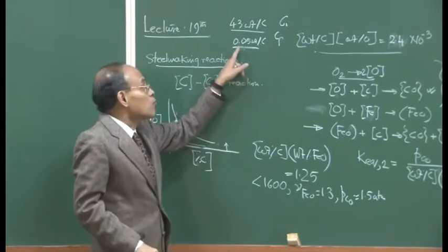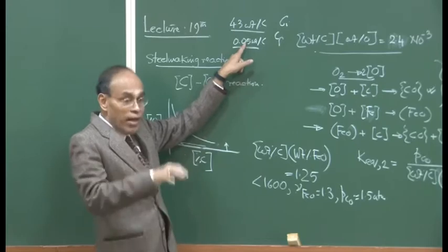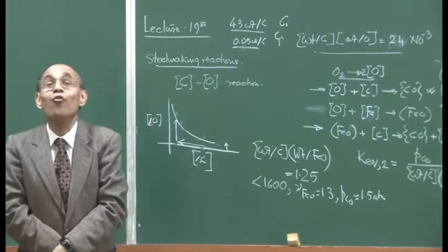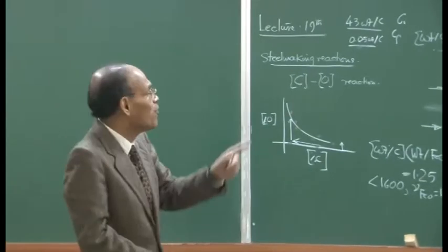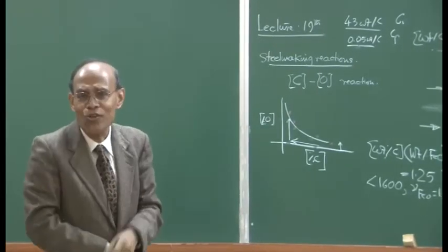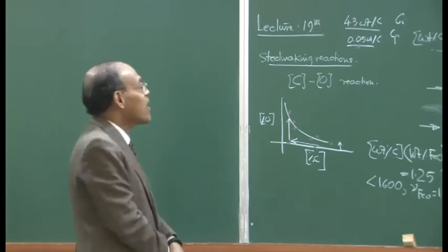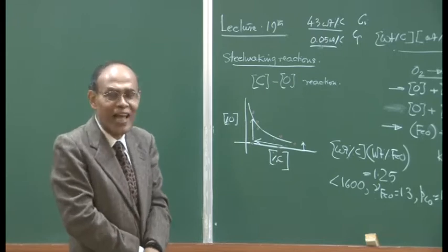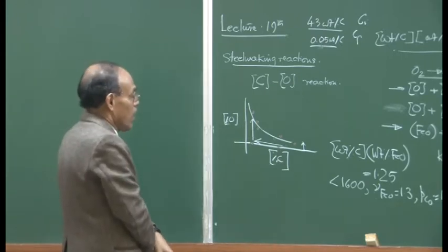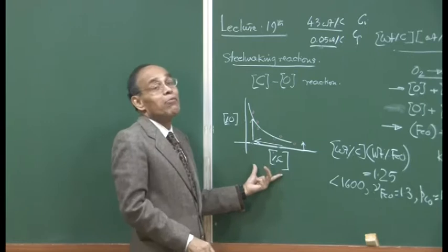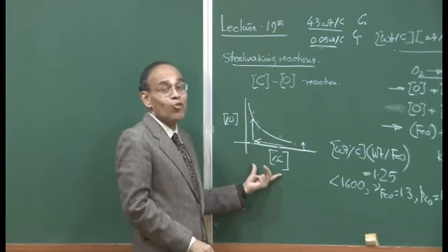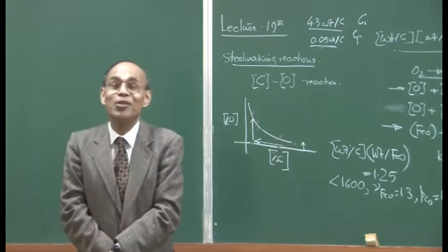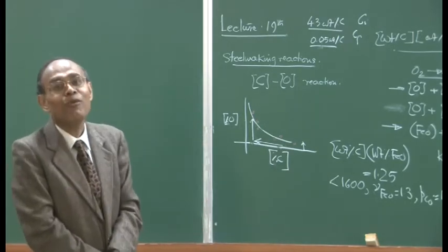And if we arrive at the target carbon and then we blow, that period is called the overblowing period. You are overblowing because you have reached your desired carbon and still you are continuing to blow, and that is going to have a disastrous consequence as far as the iron oxide content of the slag, melt temperature, refractory life, converter operating life, etc. are concerned. Thermodynamics tells us we will be able to drive carbon out, but how we drive it will determine whether we can make steel making profitable or not.